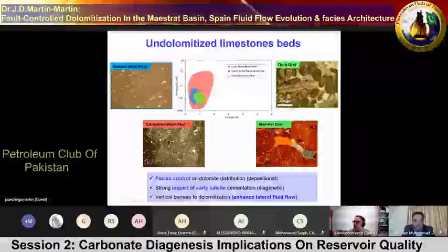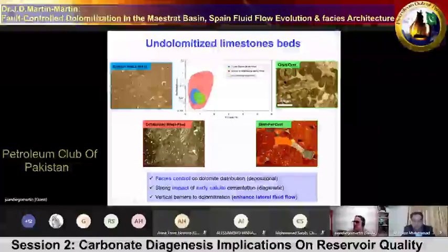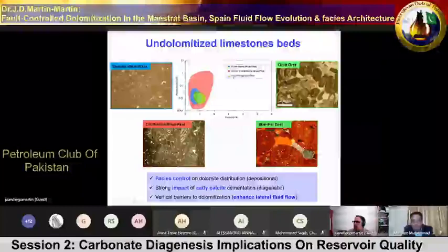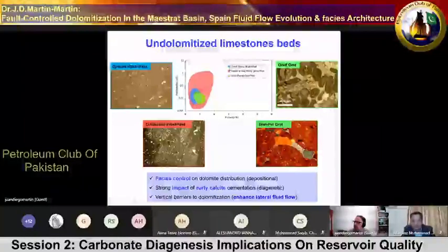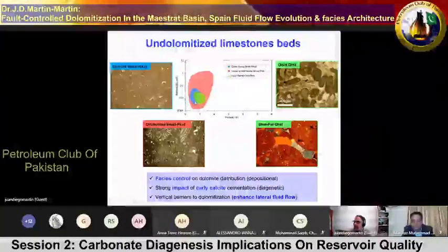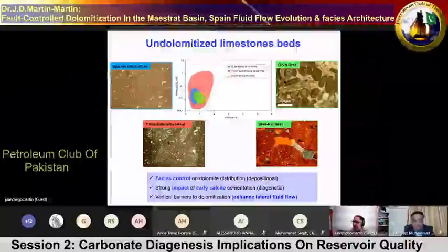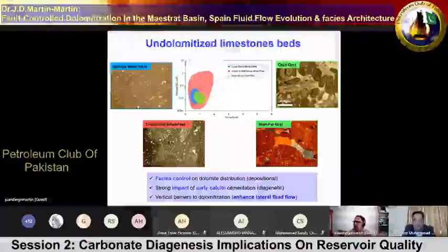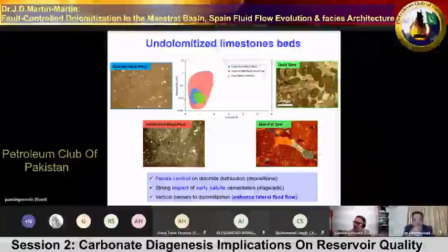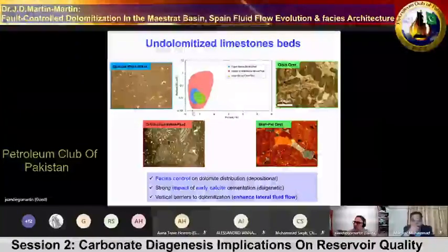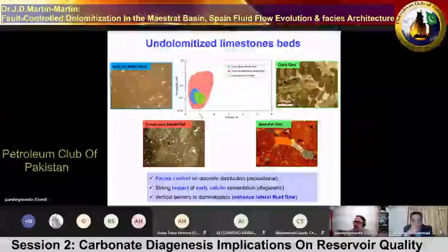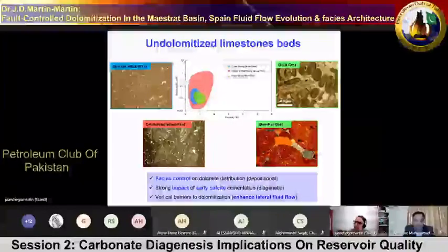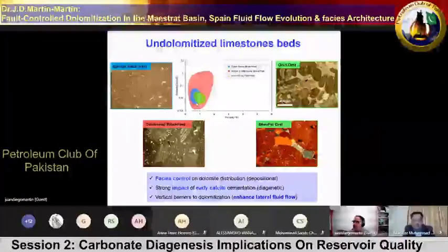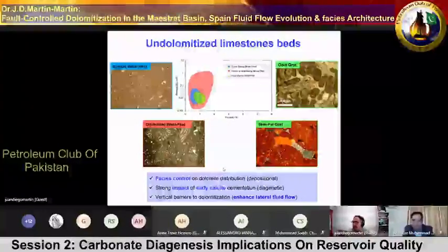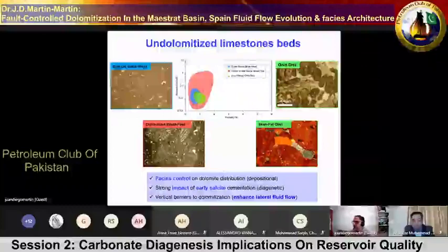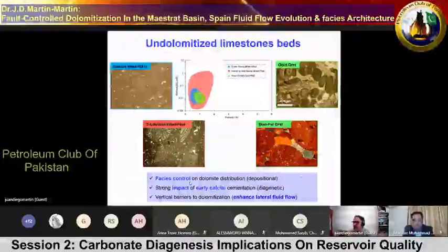So in here we have a plot with the permeability in vertical and porosity in horizontal, with different phases in blue, red, and green color. All of these again is limestone, and as you see, it's really very low porosity, between 0.5 and 1%, which is really nothing, and very low permeability. Really nothing again. So it seems that there is a facies control on dolomite distribution in here.